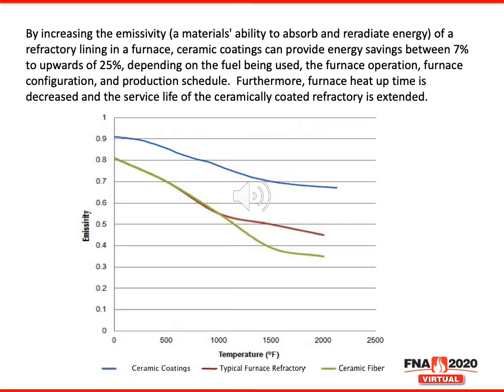One of the main functions of the ceramic coatings is to increase the emissivity, a material's ability to absorb and re-radiate energy, of a refractory lining in a furnace. These coatings can provide energy savings between 7 to upwards of 25%, depending upon the fuel being used, the furnace operation, furnace configuration, and production schedule. Furthermore, the heat-up time of these furnaces is decreased, and the service life of the ceramically coated refractory is extended. As shown in the graph below, emissivity versus temperature, you can see the values for typical furnace refractories and typical ceramic fiber versus the ceramic coatings.